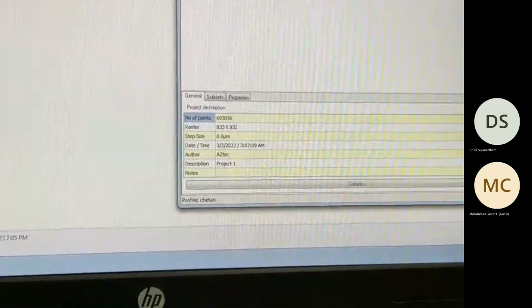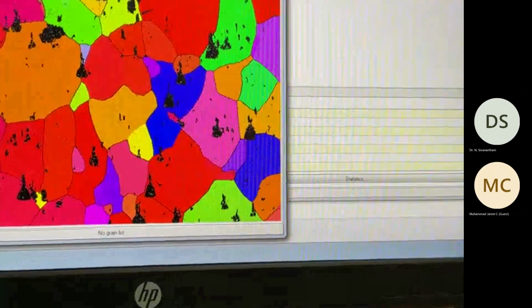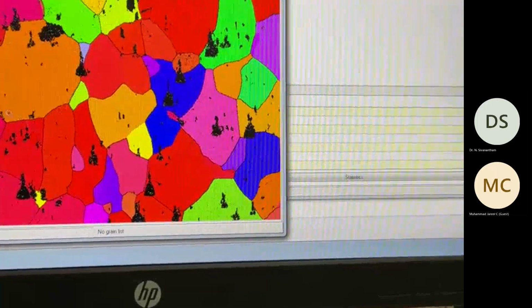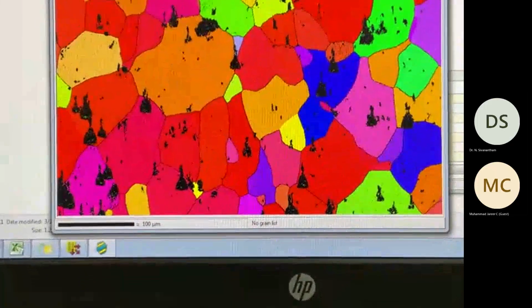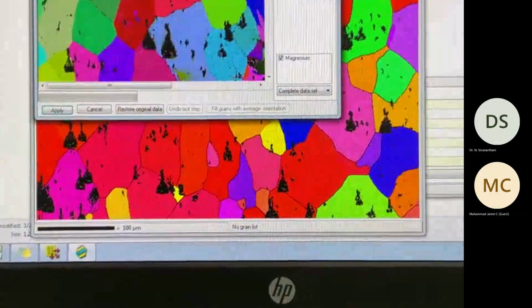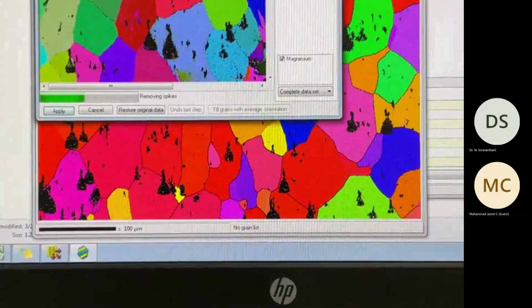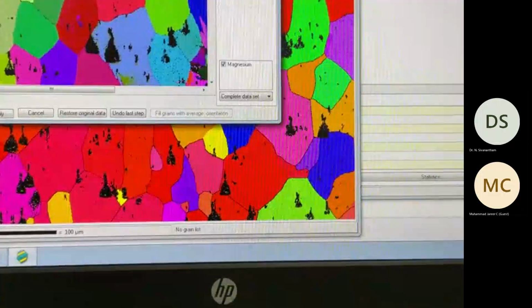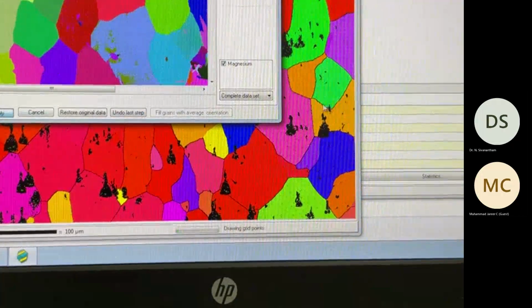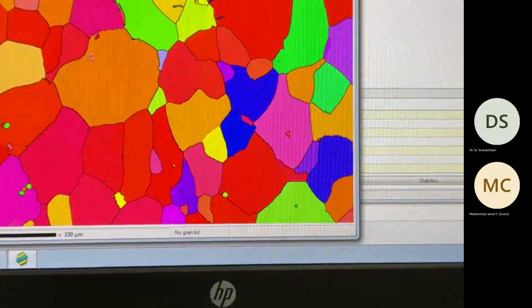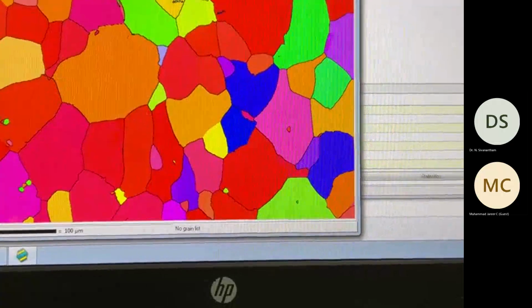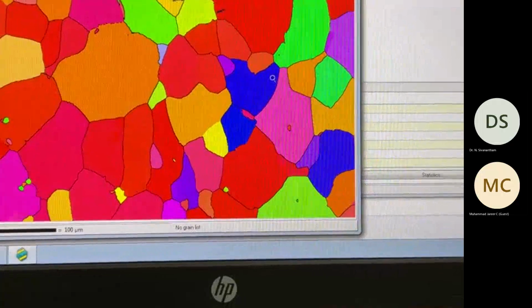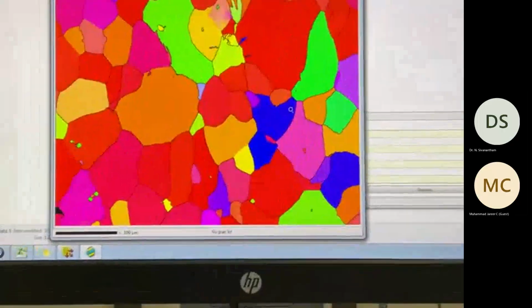The previous sample I showed was recrystallized for only a couple of minutes. This is for 1 hour. So we will see how the grain size distribution is. As you can see, this has bigger grains. The previous grains you saw were smaller grains. You can perform noise cancellation again. And now you can see that the previous sample had smaller grains and this sample has a higher grain size. You are able to see the difference, right?